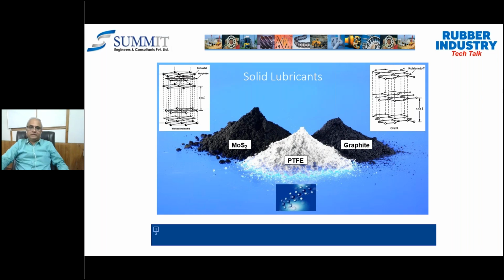So this definition is prompting us to go to the characteristics, how it could be manufactured actually, right? So there are three major solid lubricants. One is molybdenum disulfide, PTFE, and the graphite. You can see the three different colors over here. One is completely black, that is molybdenum disulfide, right? PTFE is a little whitish, and the graphite has a little brownish, though it is not properly distinct, but it is blackish with a little white color into that.